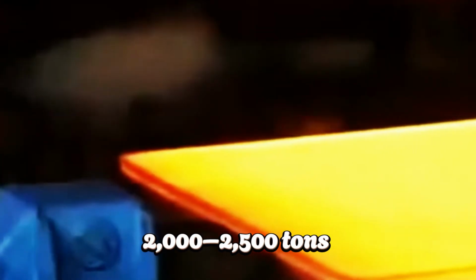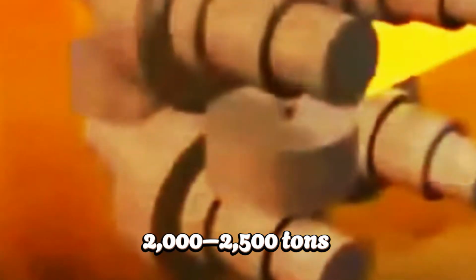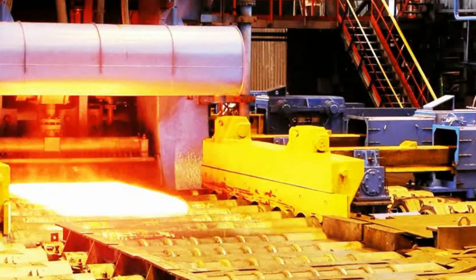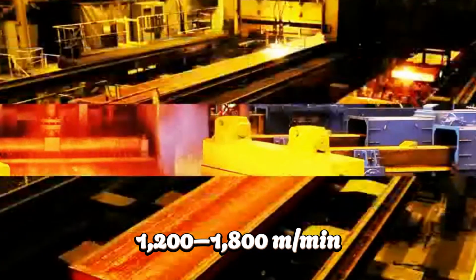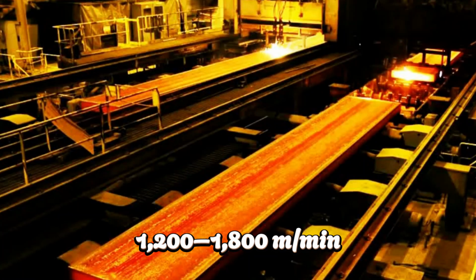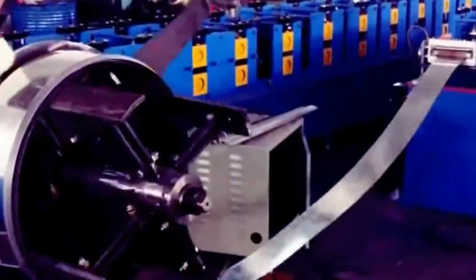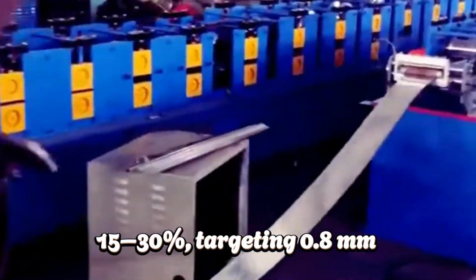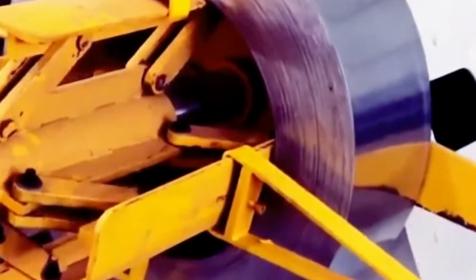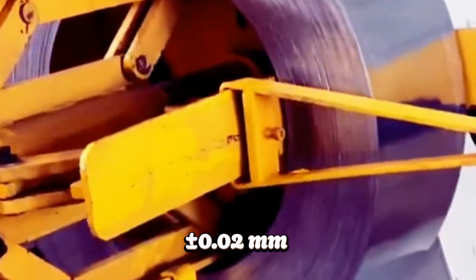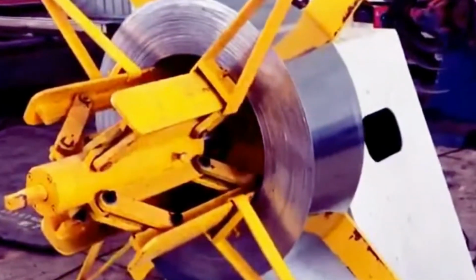Force. 6 stands apply 2,000 to 2,500 tons each. Speed climbs to 1,200 to 1,800 meters per minute. Each stand reduces thickness by 15 to 30%, targeting 0.8 millimeters final gauge. AGC reads thickness every millisecond using X-ray or laser gauges. Hydraulic actuators correct roll gap within plus or minus 0.02 millimeters instantly. Water cooling prevents roll thermal expansion.